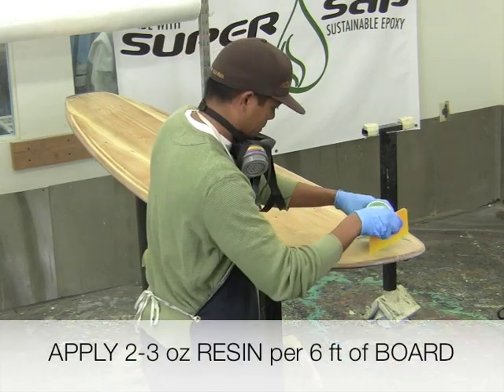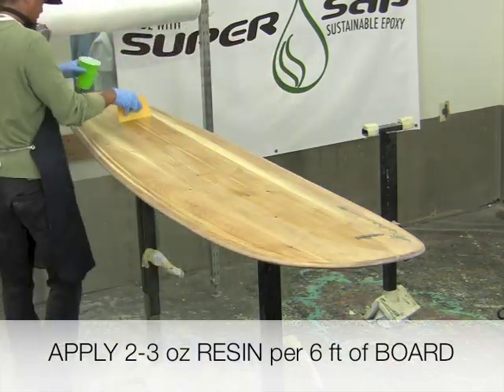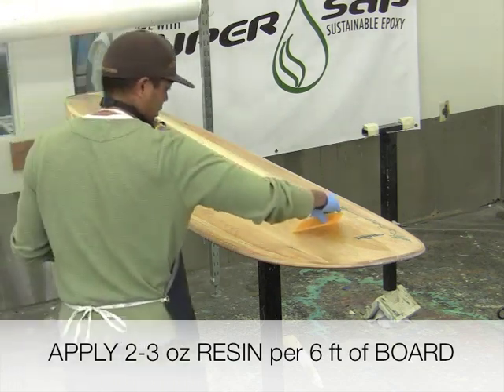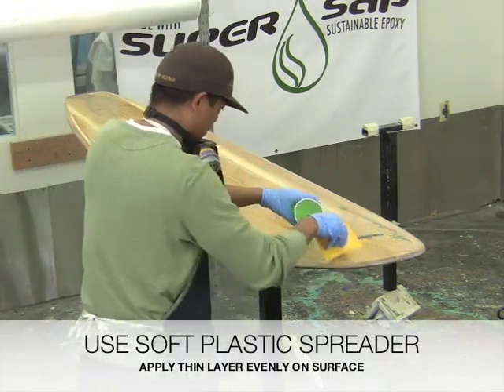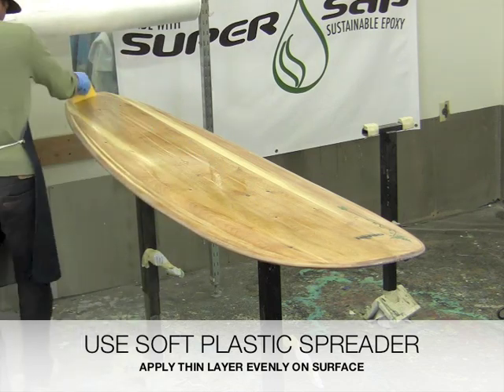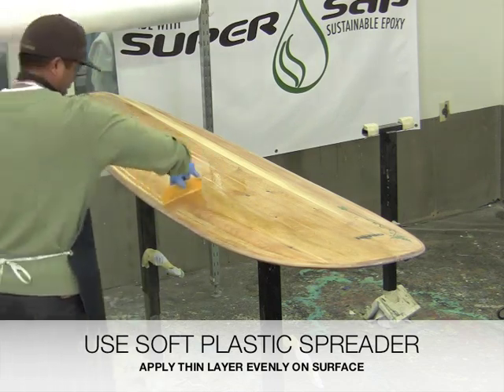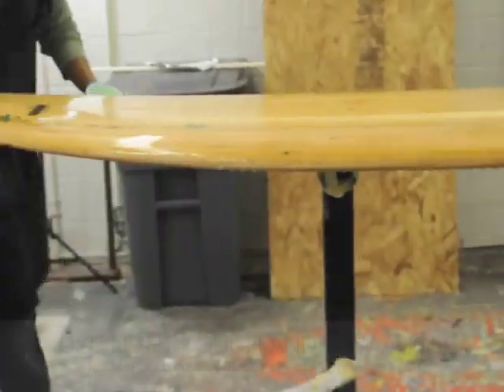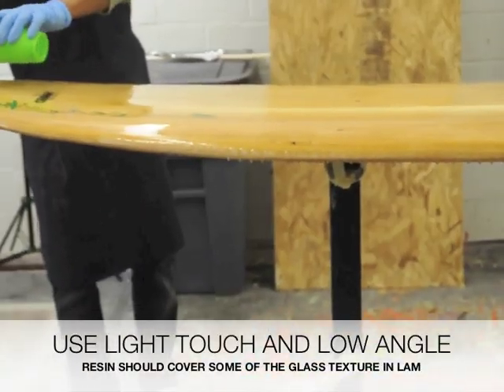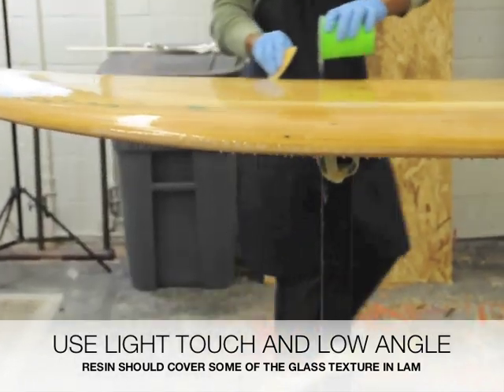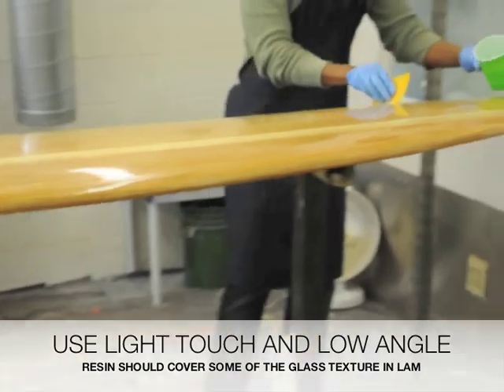Next, we're going to apply a thin paste coat or squeegee coat of resin using a plastic spreader to help fill in the texture of the fiberglass. This paste coat also provides a smooth base layer for the brush hot coat to follow.